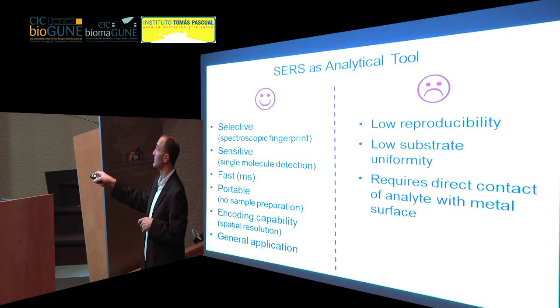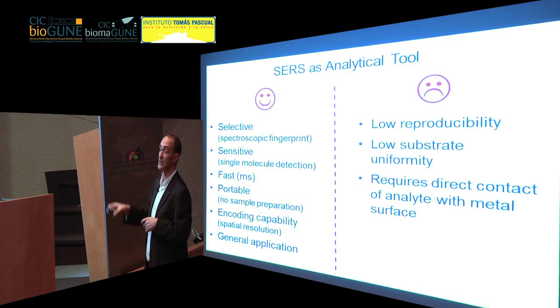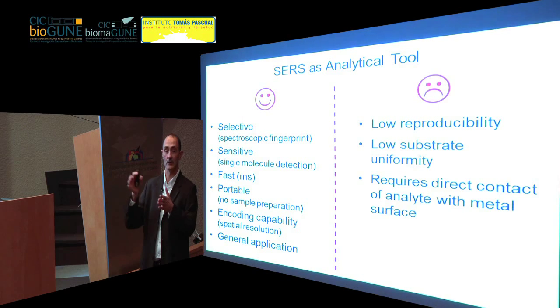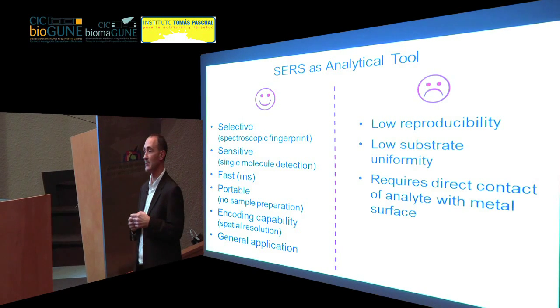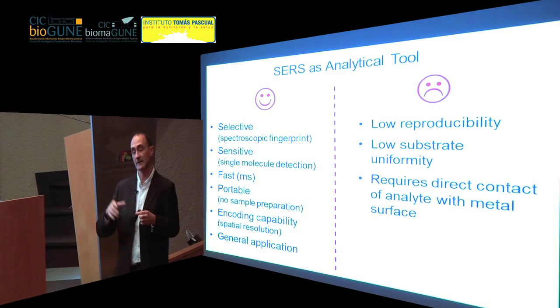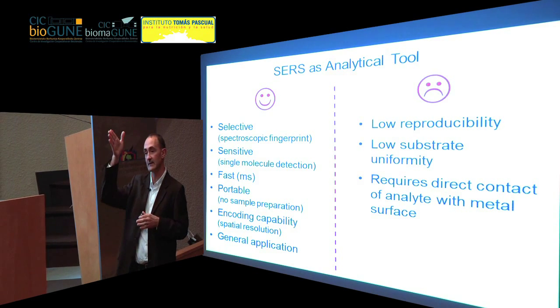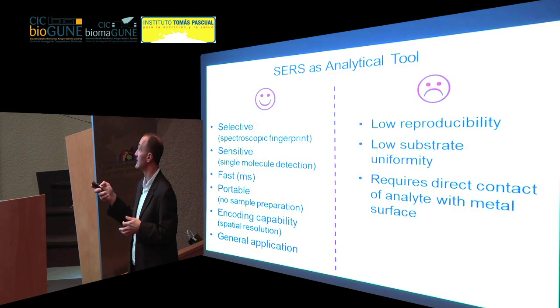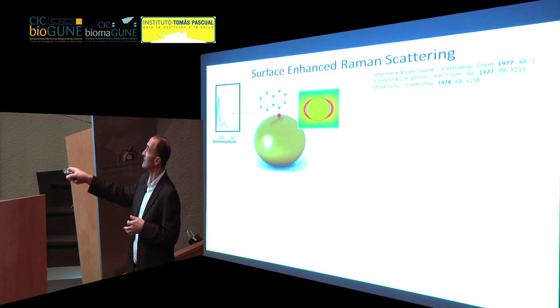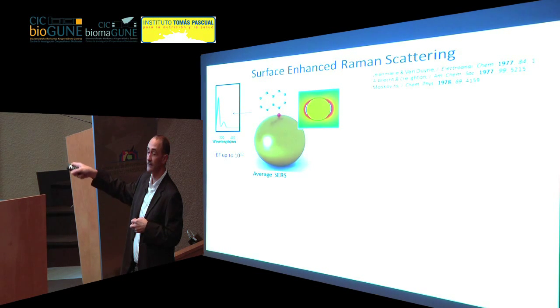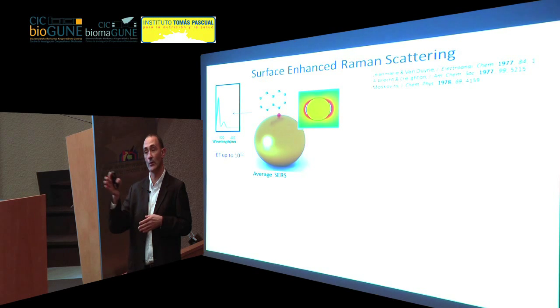Another important problem is that the analyte that you want to identify has to be very close to the surface of the particle. This is something that I probably did not stress enough. You can get this very high increase in the electric field. We can see it in this slide, actually. You can see this very high increase in the electric field, but it goes off very quickly when you go away from the surface. So only a few nanometers away from the surface, the molecule will not feel the high electric field, so you will not get the SERS effect.